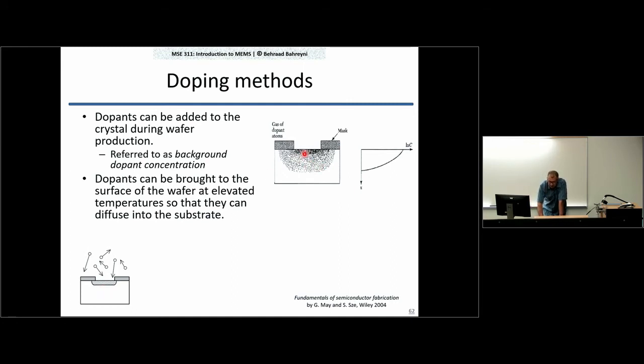And then as you expect, because you have the highest concentration of dopants at this opening at the top of this substrate, you have higher concentration of dopants here, and the concentration drops as you go deeper and deeper into the substrate. So if you look at the concentration, you have the maximum at the surface and it drops as you go deeper. So this is called doping by diffusion. You bring dopants close to the surface and you let them diffuse into the substrate. You can do it in a gas phase as shown to the left here, or in a solid phase.